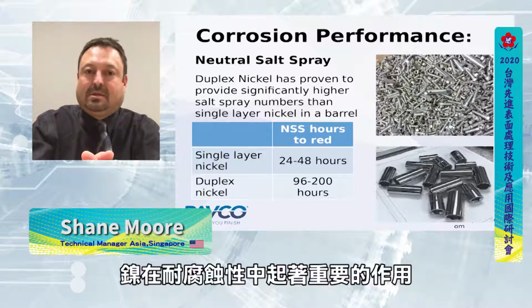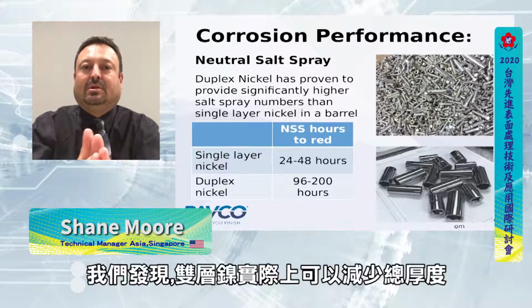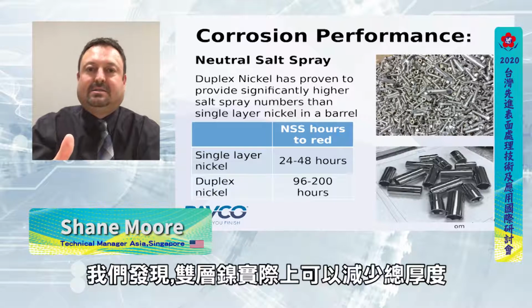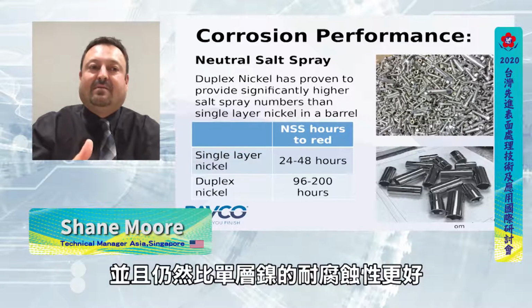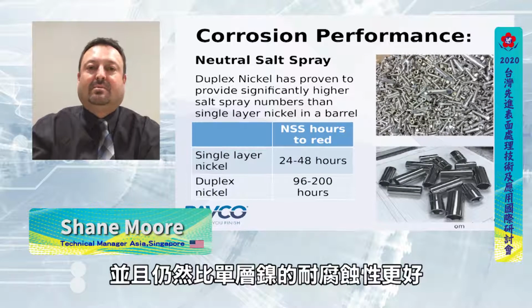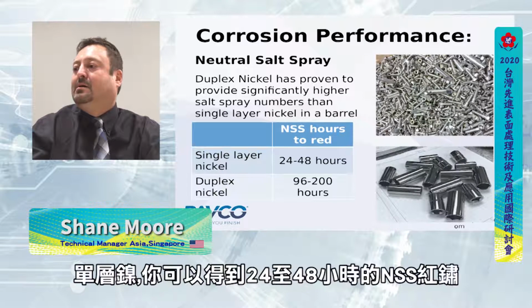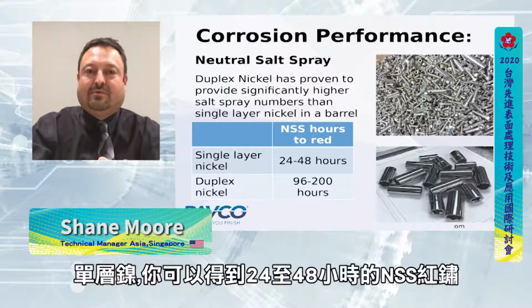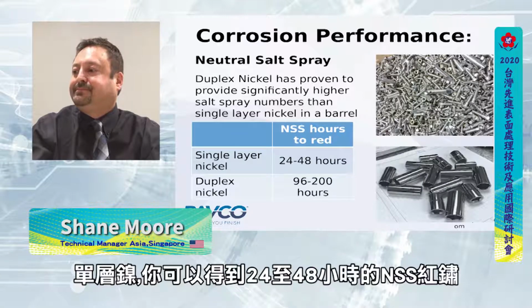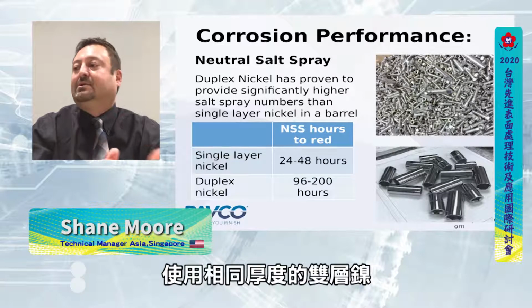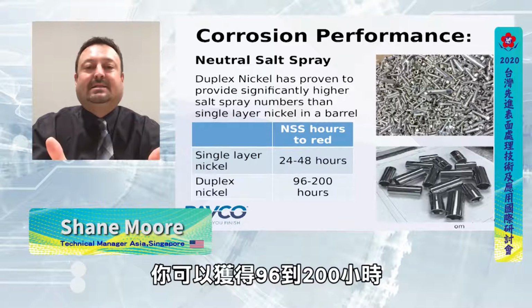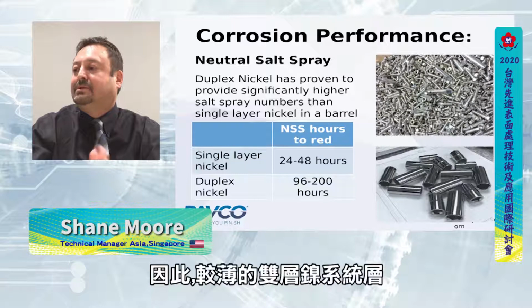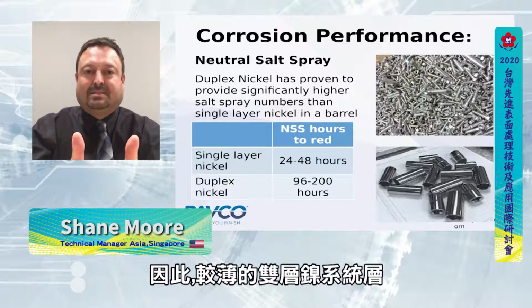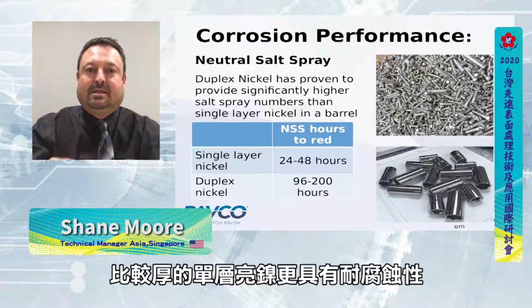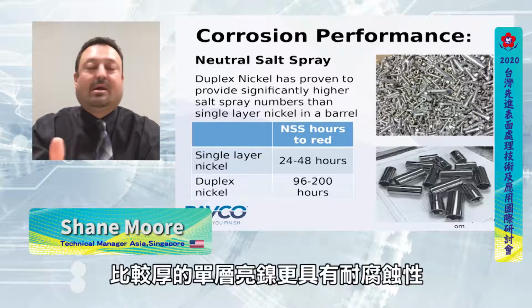The nickel plays an important role in the corrosion resistance. We found that you can have a thinner deposit of duplex nickel and still have better corrosion resistance than a much thicker deposit of one layer of nickel. A single layer of nickel, you can get about 24 to 48 hours of neutral salt spray to red rust. With a duplex nickel, if it's the same thickness, you can get 96 to 200 hours. So like I said, a thinner layer of a duplex nickel system will have more corrosion resistance than a thicker layer of a single bright nickel layer.